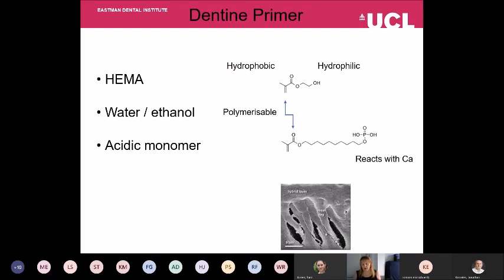If we look at the composition of the dentine primer, it usually consists of HEMA, which is hydroxyethyl methacrylate. What you have in HEMA is a hydrophilic OH group, which allows it to dissolve in water and mixtures of water and ethanol. But it also has a methacrylate group, a C double bond C group, that is polymerizable.